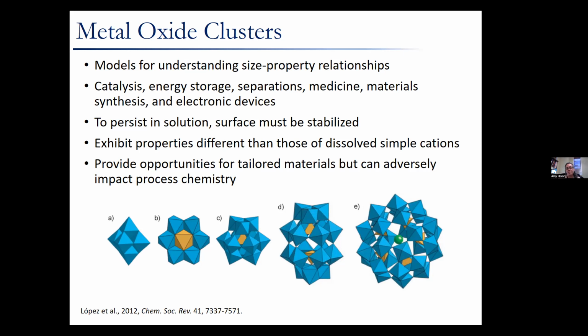However, in order to persist in solution, the surface must be stabilized so that it doesn't continue to grow and then precipitate from solution. This stabilization can take several different forms. The polyoxometallates that are shown at the bottom of the screen here have double bonded oxygens, which we call oxo oxygens, that are used to stabilize the surface. But we could also have inorganic species such as the halogens or nitrate, or even organic ligands that serve to stabilize the surface of these nanoclusters.